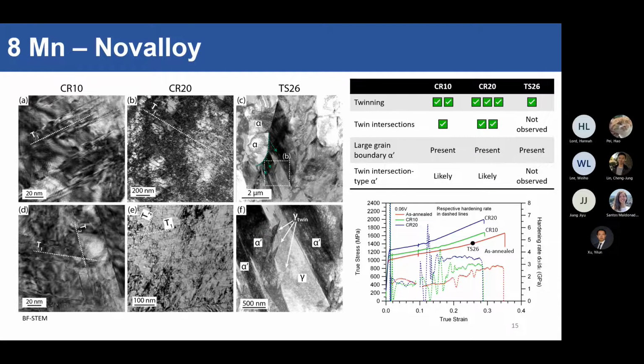So what this tells us is that twinning in medium manganese steels is strain path dependent. Whether you cold roll it or uniaxial tensile, it makes a difference to your amount of twins that you form. And the difference to the amount of twins therefore affects the density of twin intersections, which are the potent nucleation sites for martensite to form, right? So by cold rolling it, you're introducing more twins and therefore more twin intersections, and that is an alternate pathway to form martensite compared to pure uniaxial tensile. Because when you only do a uniaxial tensile, you don't form these twins. You don't really have a lot of twin intersections, so you can only really form these very large grain boundary martensites.